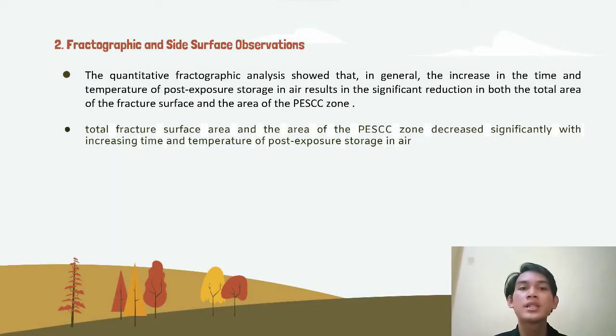2. Fractographic and side surface observation. The quantitative fractographic analysis showed that, in general, the increase in the time and temperature of post-exposure storage in air results in a significant reduction in both the total area of the fracture surface and the area of the PESCC zone. Total fracture surface area and the area of the PESCC zone decreased significantly with increasing time and temperature of post-exposure storage in air.